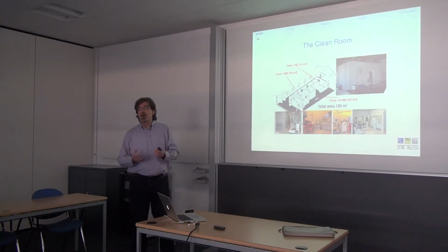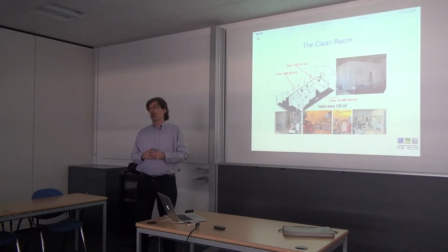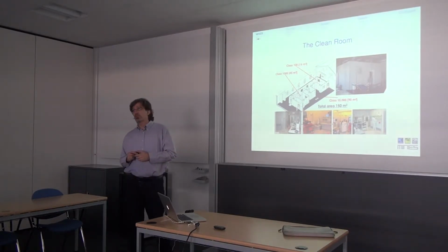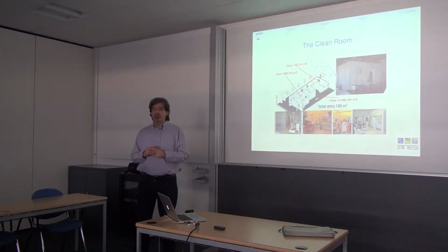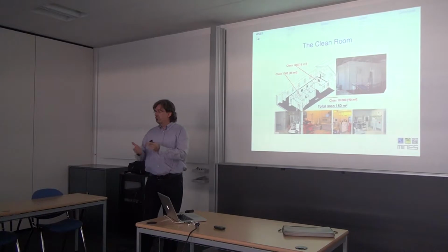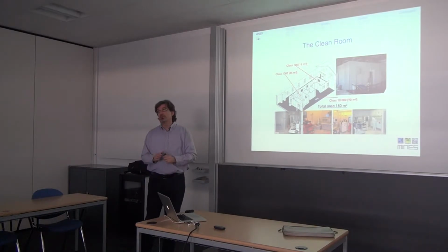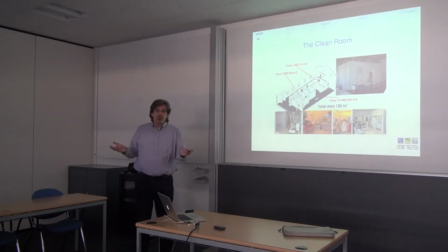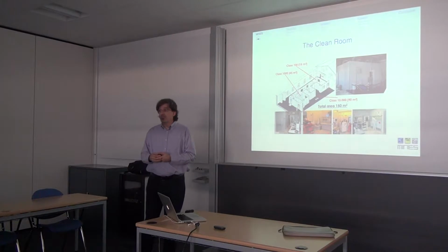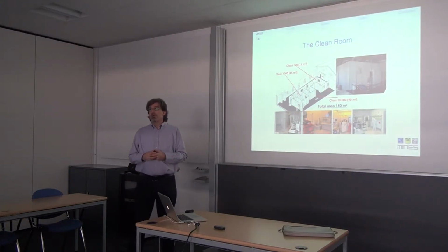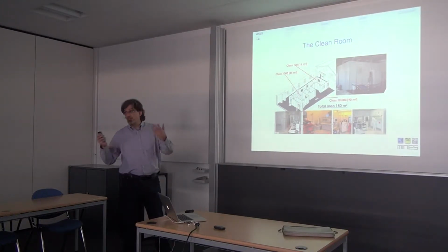We arrive up to a resolution of 5 microns. We are building for a few applications also devices with 1-2 microns, but to be sure to have good reproducibility of the results, we can stay around 5 microns. That for MEMS is not too bad. You can do a lot of applications, a lot of devices.